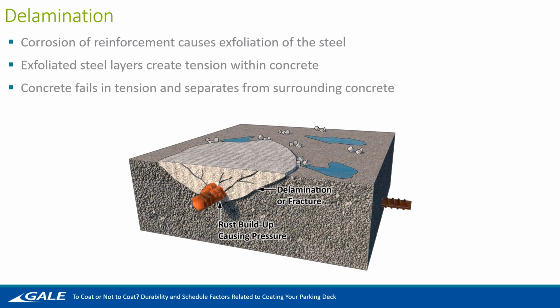So as this outward tension force is applied to the concrete, it's basically going to be pushing away the sound concrete from the unsound concrete that's below the rebar. So it will be creating this gap, as you can see by the delamination or fracture arrow on the illustration below. It's important to note that delamination isn't visible from the surface. It's only beneath the surface that it's creating that gap. And with that gap, it allows more water to pool in, more chlorides to get in, and just exacerbate the issue and the corrosion.